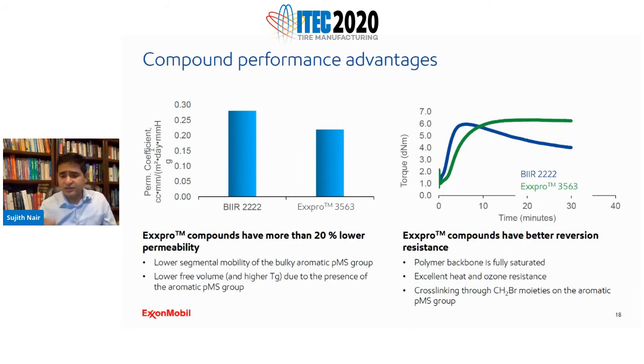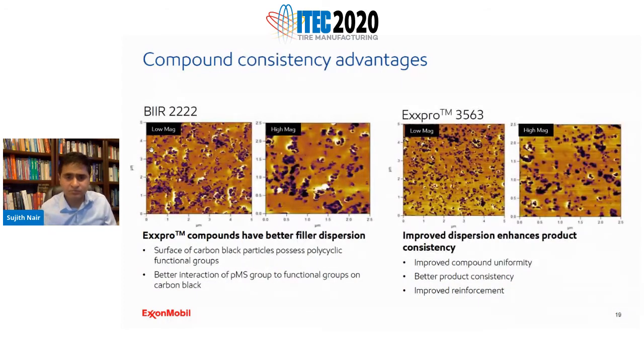Now, the other thing that we said earlier is that, again, Exxpro is a fully saturated molecule. There's no unsaturation, no double bonds. And so, as you can see in the torque curve shown on the right-hand side, Exxpro literally does not have any reversion. As you cure the polymer, it gets overcured, and then you have degradation because of the cleavage of these double bonds in bromobutyl. That's the dark blue curve. As you can see, the green curve, Exxpro 3563, has literally no reversion because there are no cleavage points. And the cross-linking happens mainly because of the CH2Br moieties.